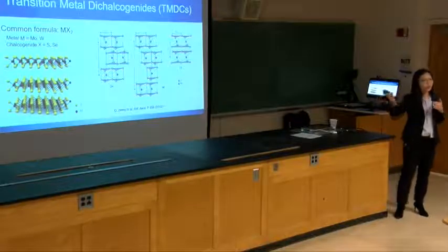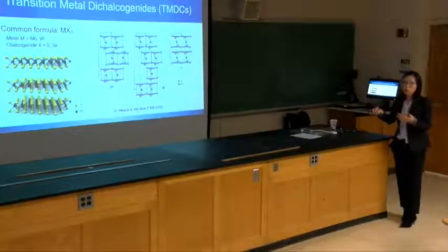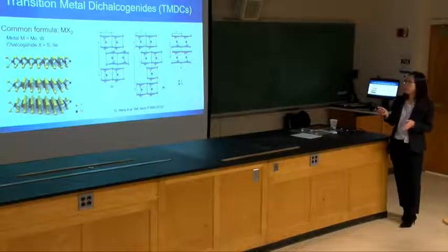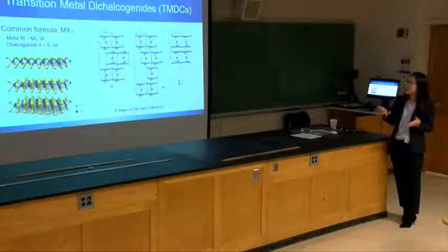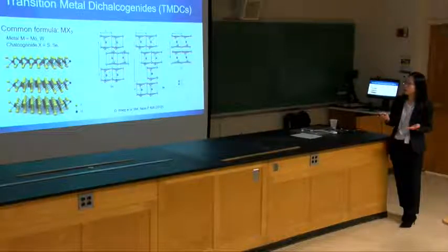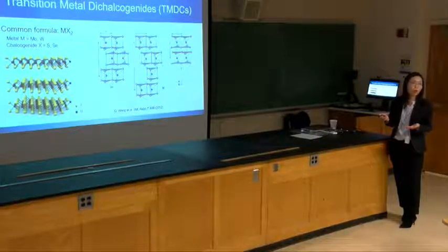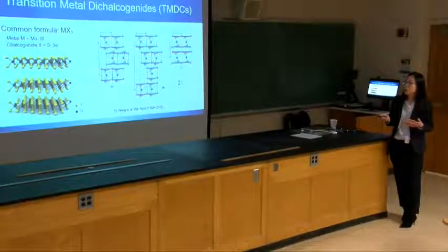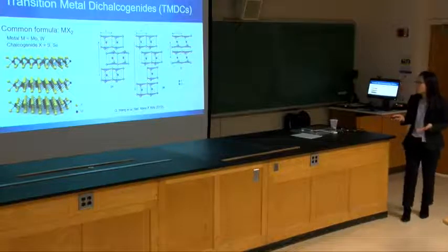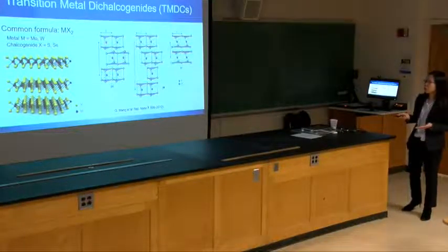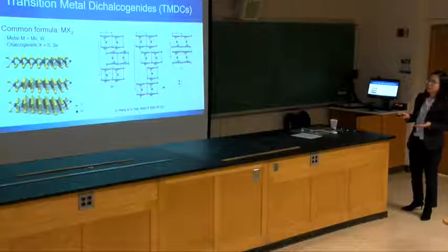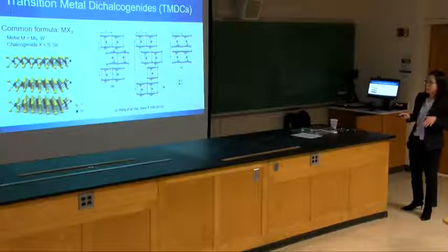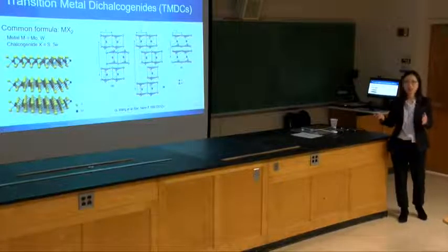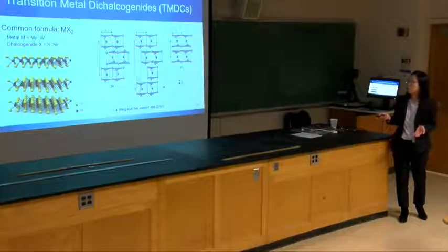But in addition to that, there's also an interesting aspect of using layer materials as a host for quantum emitters. At this point, it's very important to go back to the properties of the host. The host is tungsten diselenide, a typical transition metal dichalcogenide. It goes with the common form MX2, with M denoting the metal, and X the chalcogen, sulfur, selenium. Normally there are three kinds of stacking, 2H, 3R, and 1T. I actually worked a lot on 3R stacking during my PhD, but in this presentation, I will focus more on 2H, as it's more common in nature.